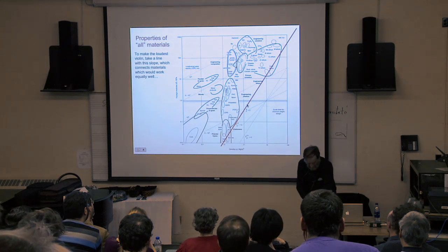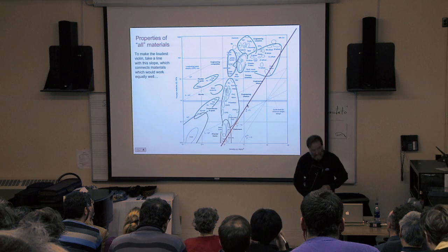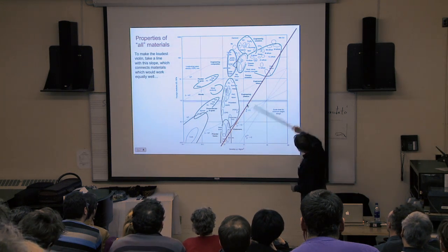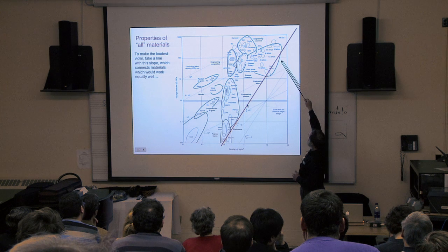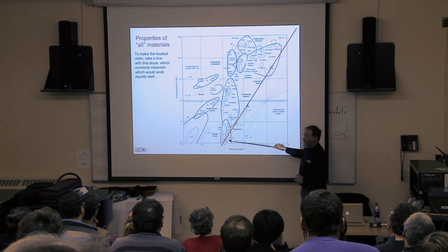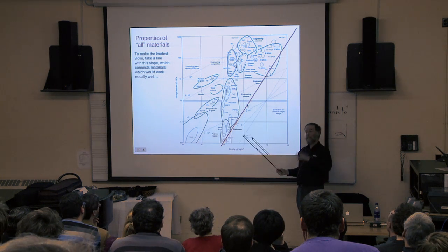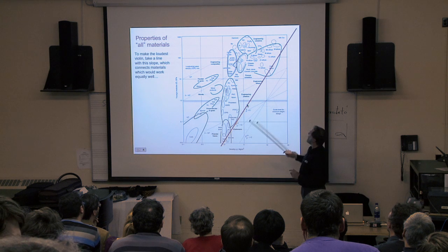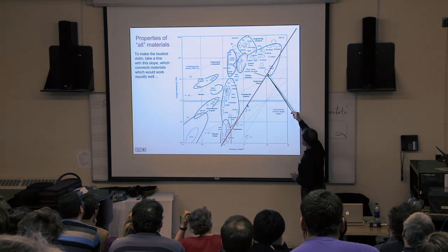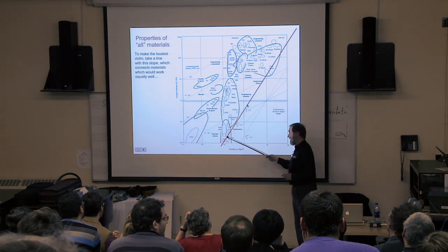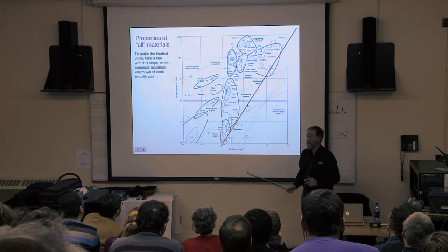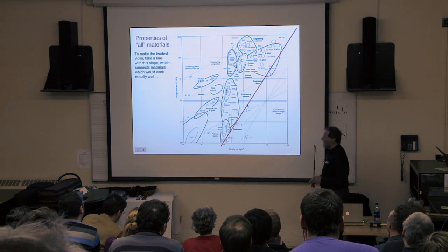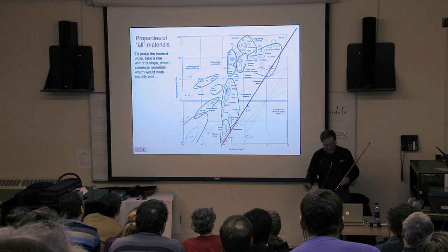And it turns out that there are particular lines in this diagram with a particular slope here on these log scales, where any 2 points along this line would make violins which were equally loud. So if you made a violin out of lead here and silicone rubber here, they would be equally loud. That's not very loud, it would not be an easy thing to do in either case, but they would be as loud as each other.